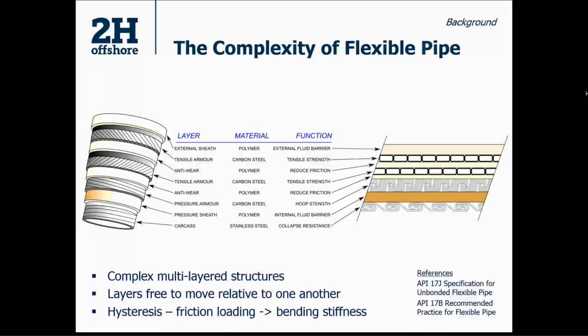And hysteresis in flexible pipes is caused by the friction loading on the tensile armor wire layers, and that's generated in response to bending and the contact pressures that occur between each of the layers. So this affects risers that operate with high internal pressures or that are in deep water and have large external pressures as a result, and/or high tension loads. What this does is it modifies the bending stiffness quite significantly.